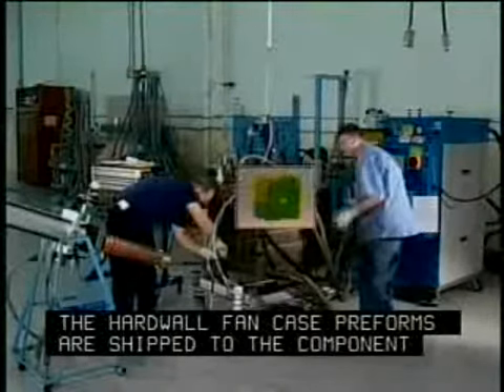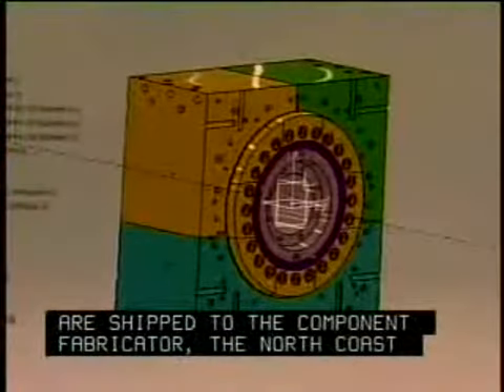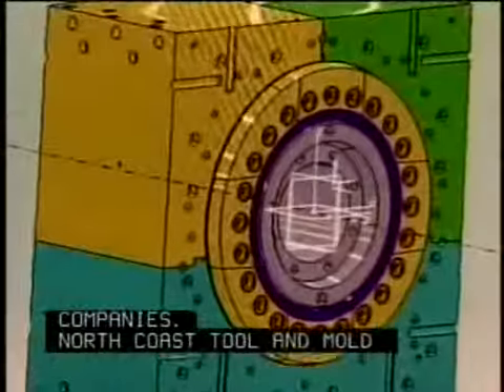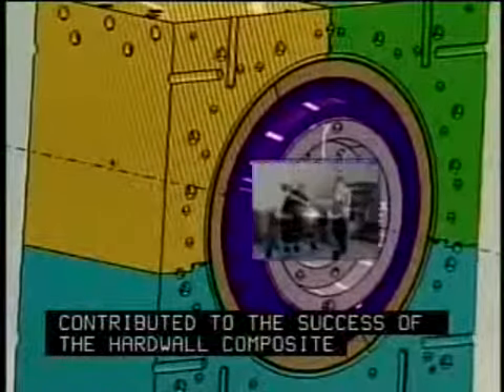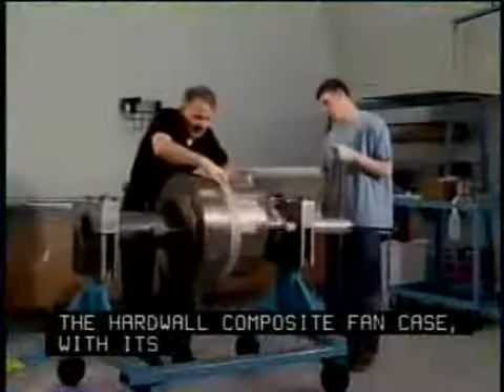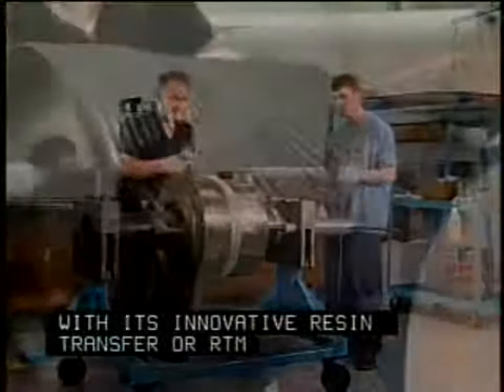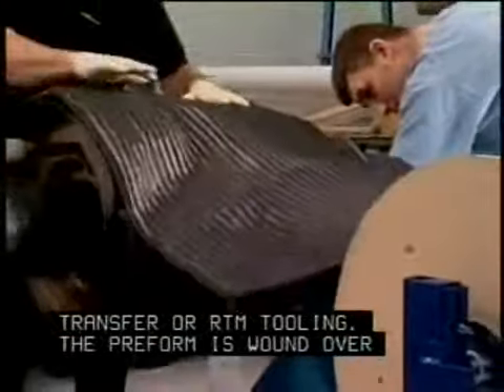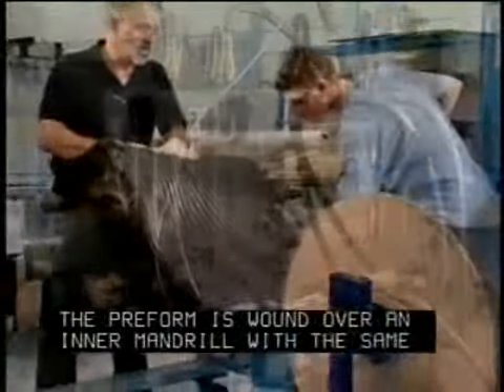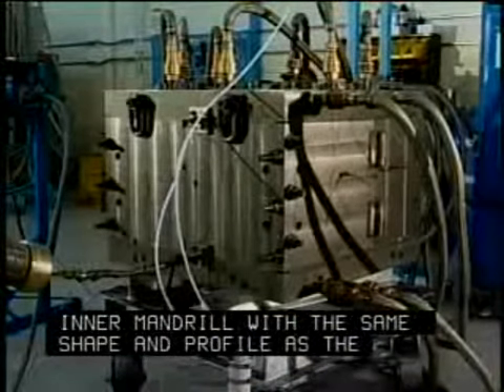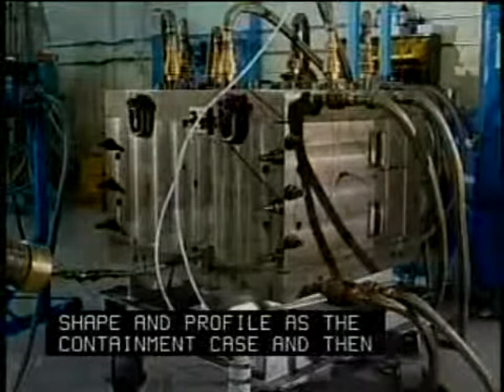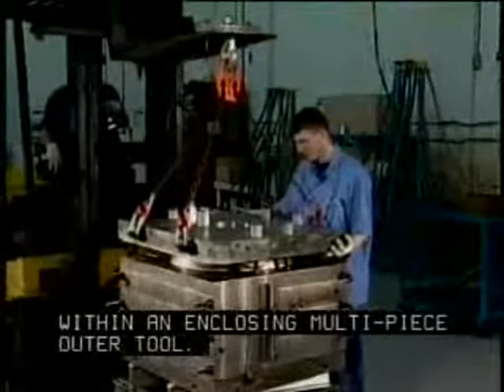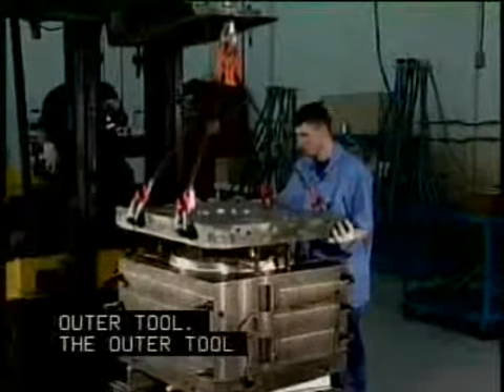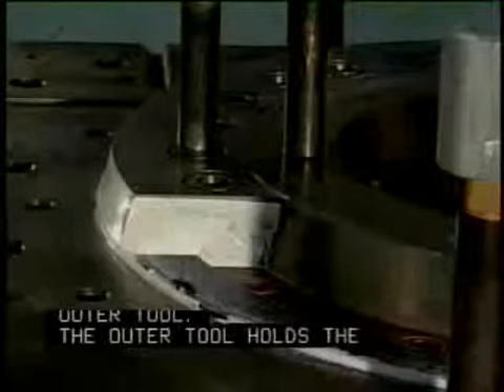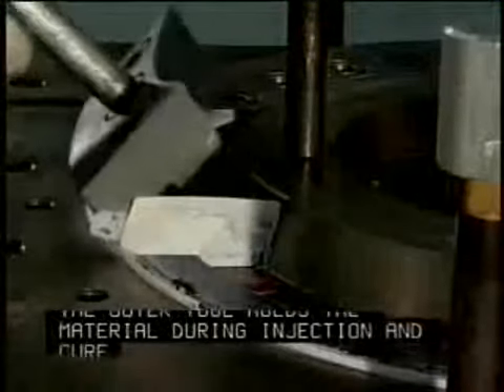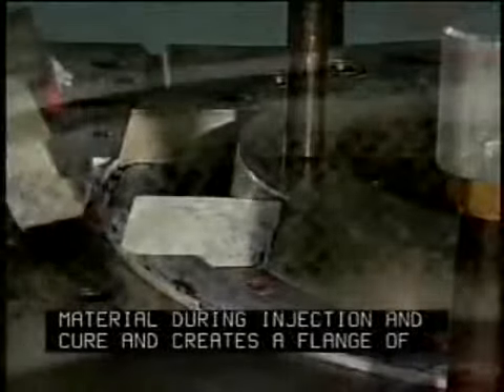North Coast Tool and Mold contributed to the success of the hardwall composite fan case with its innovative resin transfer, or RTM, tooling. The preform is wound over an inner mandrel with the same shape and profile as the containment case, and then placed within an enclosing multi-piece outer tool. The outer tool holds the material taut during injection and cure, and creates a flange of uniform and robust thickness through which attachment holes can be drilled.